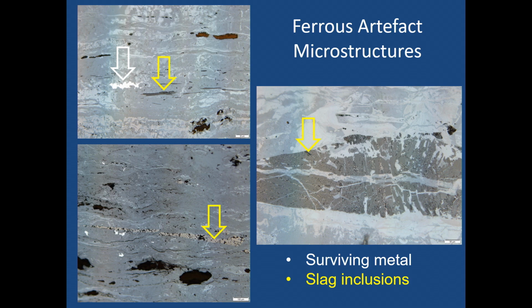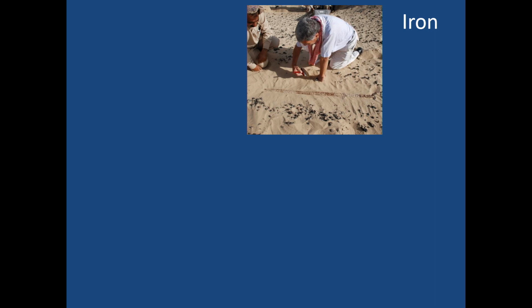They're stretched out and they're bashed around, but they're still in there from the smelting process. And Ivan's study of these and of the morphology has demonstrated quite conclusively that despite our hundreds of kilograms of iron artefacts, there's absolutely no evidence for primary iron making at the site whatsoever.